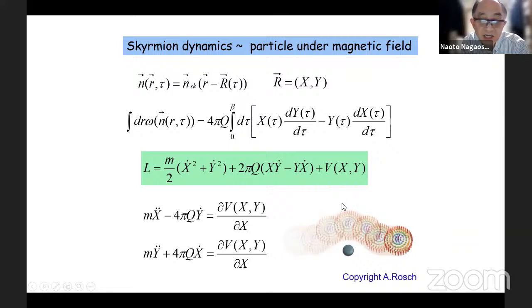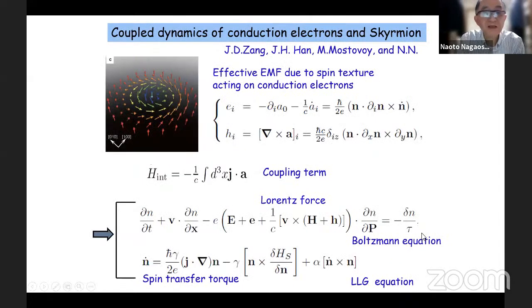So actually, this is the reason why the skyrmion is so mobile, and the threshold current density for the skyrmion motion is very low compared with the domain wall motion, etc. So that's one of the main reasons why the spintronics people are quite interested in the skyrmions as information carriers. But the basis of this high mobility is coming from this Berry phase of the spin and the noncollinear spin structure of skyrmions.